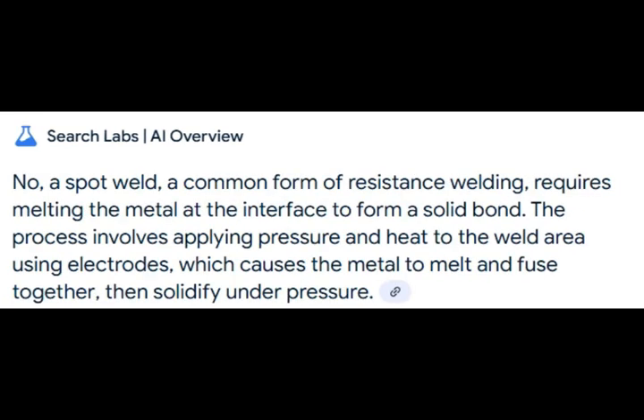No, a spot weld, a common form of resistance welding, requires melting the metal at the interface to form a solid bond. The process involves applying pressure and heat to the weld area using electrodes, which causes the metal to melt and fuse together, then solidify under pressure.